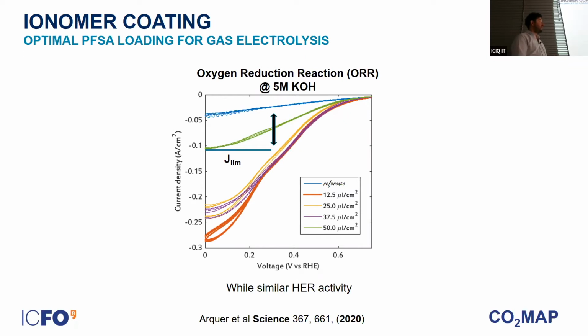But what we see is that when we change the loading of the ionomer, we could really increase the limiting current, meaning that we are, a priori, increasing the availability of the reactant, which is oxygen in this case. And all of this happened, importantly, while the activity for hydrogen evolution reaction at higher potentials was still the same. So in principle, we suspected that the only thing we were changing was the availability of the gas.